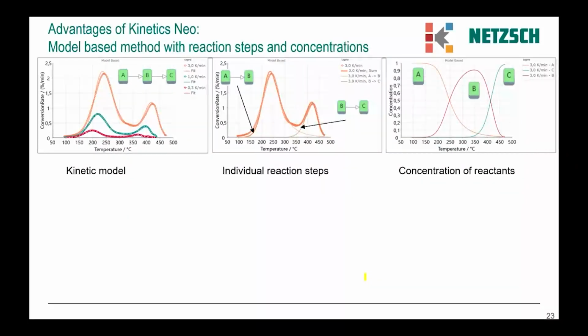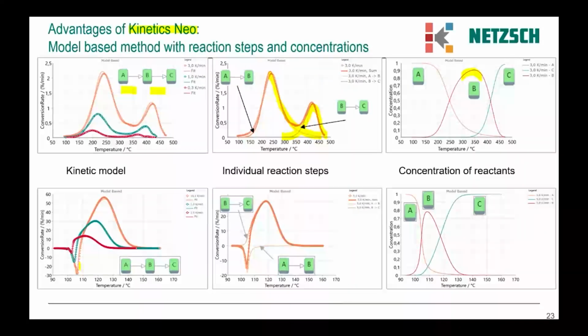Sometimes Kinetics Lite cannot work for very complex situations, and here I would like to show a couple of them. For example, for double-step kinetics, our Kinetics Neo can show each peak here separately. Then it can show the concentration of each reactant and product, and also of the intermediate reactant during the reaction. It can make analysis for a situation where we have steps of different direction, exothermal and endothermal together. Here is one step and here is another step.